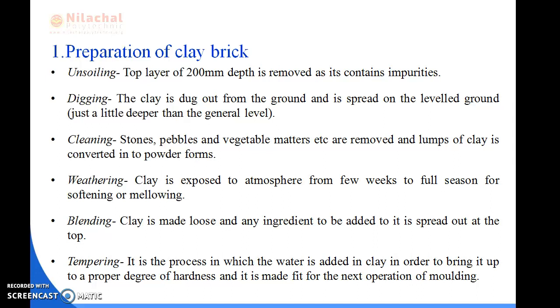Next, weathering. After all the particles have been removed, the clay is exposed to the atmosphere for a few weeks to make the clay soft. After the clay is soft, if any ingredient is to be added, it can be sprayed on top. Next process is tempering. After all these processes, water is added to the clay to make a paste, or to give a proper degree of hardness, to make it fit for the next operation, that is molding.